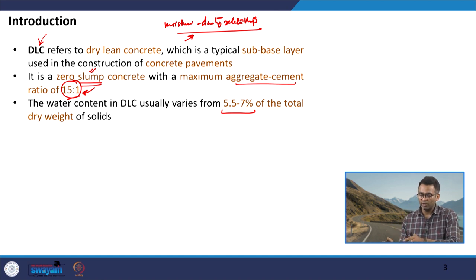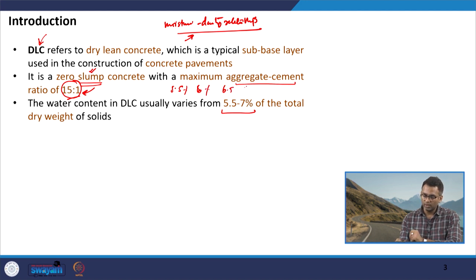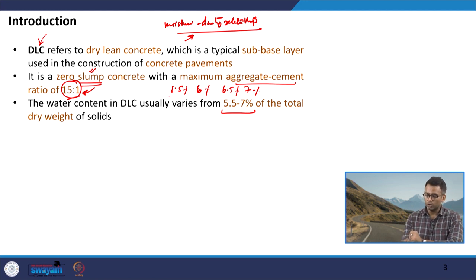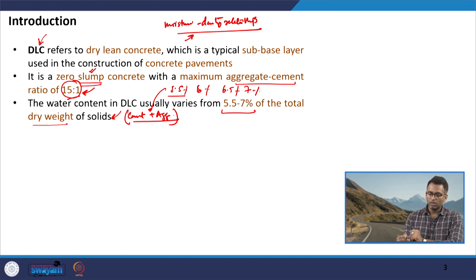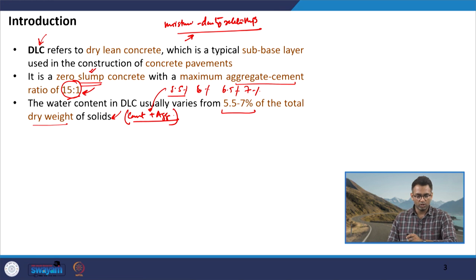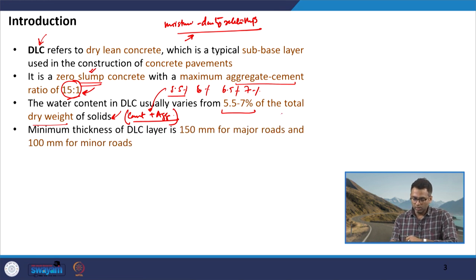We can have a gap of 0.5 percent: the first sample at 5.5 percent moisture content, the next at 6 percent, then 6.5, and then 7 percent. These moisture contents are defined by the dry weight of the solids, which are cement and aggregates. So 5.5 percent is by the combined weight of the solid materials used in the concrete mixture.